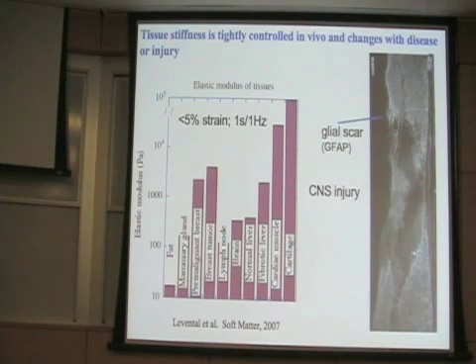Okay, so another motivation for looking at the mechanical effects is that mostly bioengineers have measured the elastic moduli of any tissue that they can get their hands on. And there's a vast literature that we've made some weak attempts to cull together. And in the literature, of course, it's confusing, but one of the things that is important, because as Jean-Francois mentioned a couple of days ago, all of these cells and even many of the tissues are viscoelastic liquids in some sense, or viscoplastic materials, that they act as very good elastic materials if you strain them on the time range of a few seconds or a hertz in an oscillatory measurement, and if you don't strain them too much. So in a roughly linear elastic regime of a couple percent strain and about a 1 second time scale, there's a pretty large